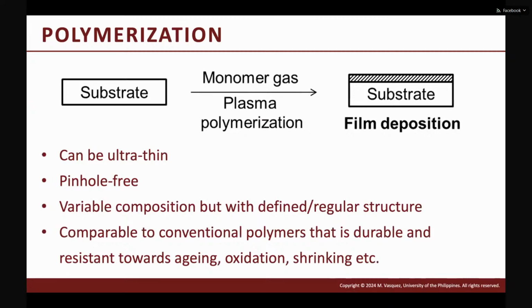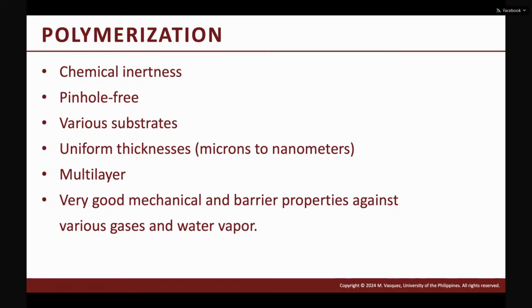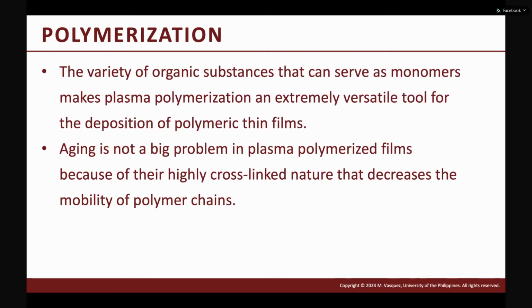Then we also have polymerization. Polymerization is more permanent, and it's really thicker compared to functionalization and grafting. So this can give thin, pinhole-free films, and you can vary the structure or composition of your polymer films. Depending on the monomer that you're using, you can achieve chemical inertness and pinhole-free films. You can use these on various substrates. Thickness is variable, from nanometers to micron-thick films. And of course, you can have multi-layered films. Aging also is not a problem because the film is really near its bulk property, so there will be no more rearrangement of the functional groups on the surface.